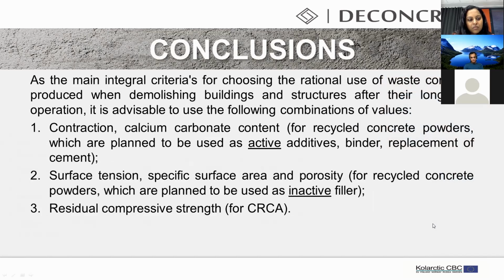So the conclusion: the main integral criteria for choosing the rational use of waste concrete produced when demolishing building construction after long-term operation, it is advisable to use the following combination of values. Contraction and calcium carbonate content, but only for recycled concrete powders which are planned to be used as active additives, binder, replacement of cement. For powders which are planned to be used as inactive filler, it is more important to know surface tension, specific surface area, and porosity. And as for coarse recycled concrete aggregate, residual compressive strength will be the main criterion for choosing.